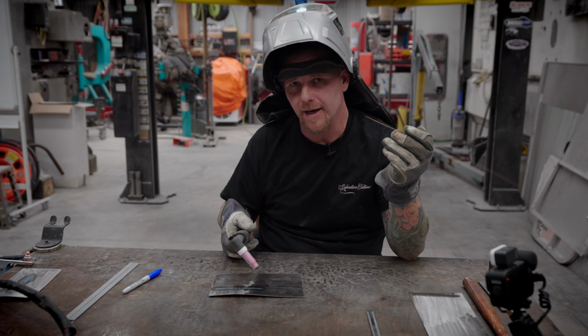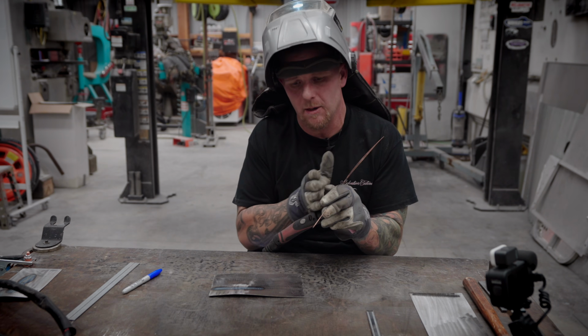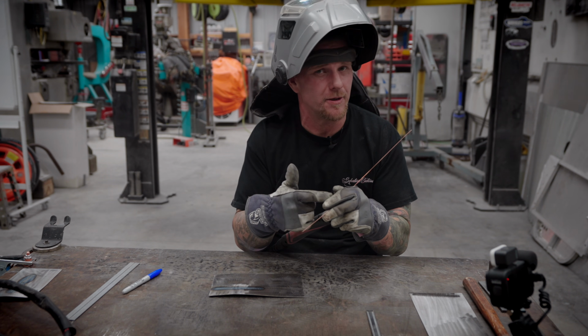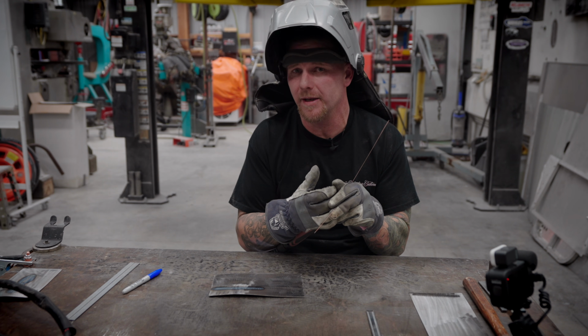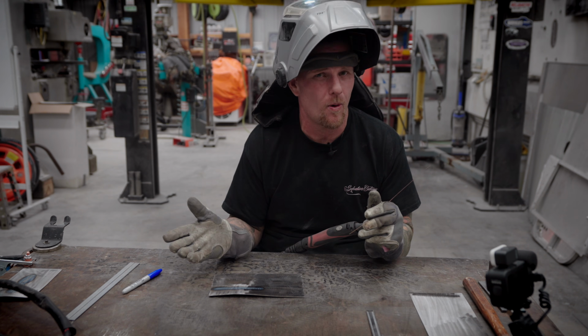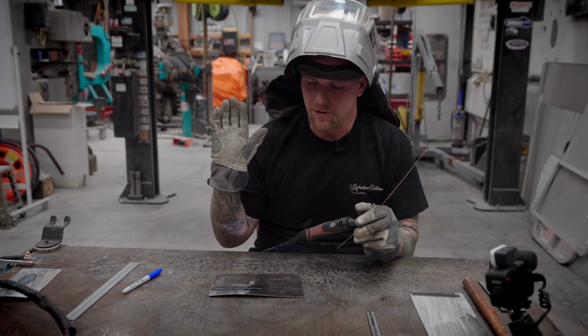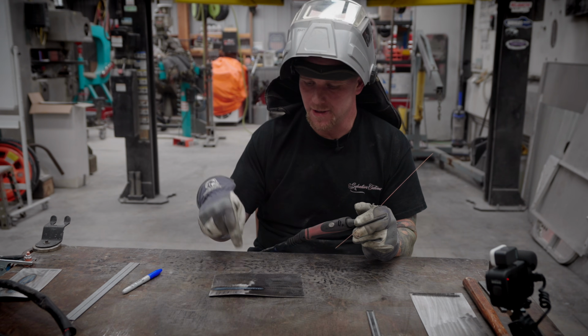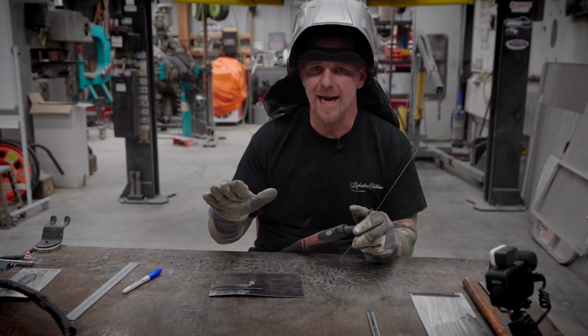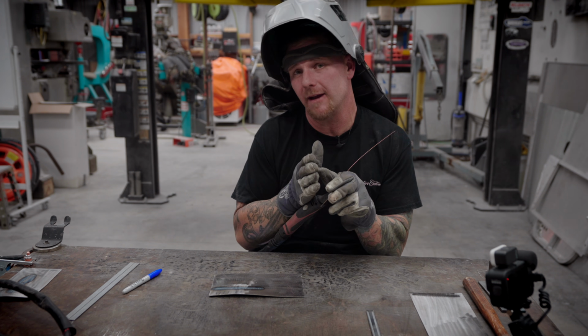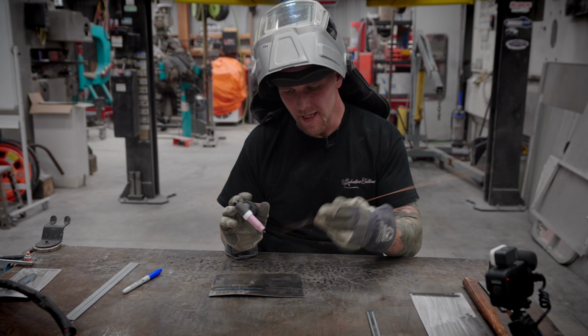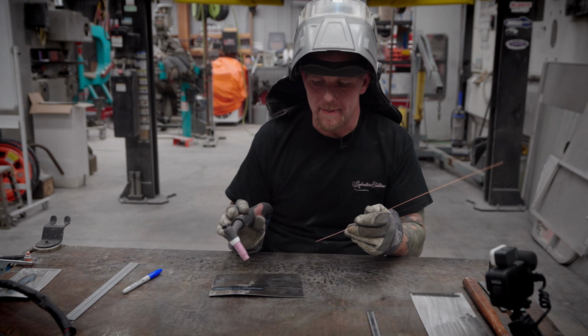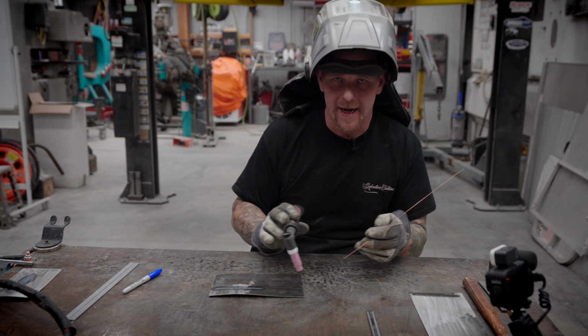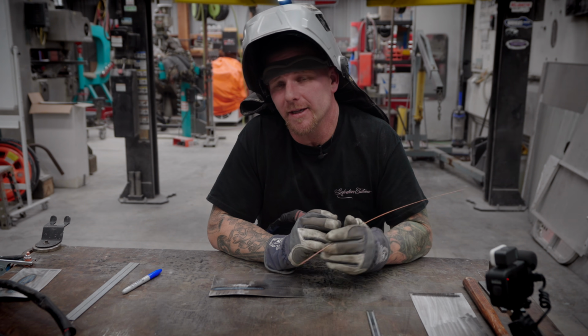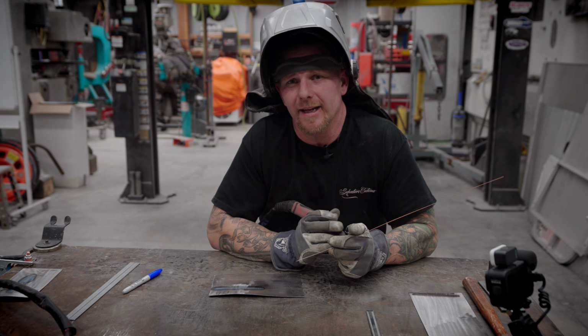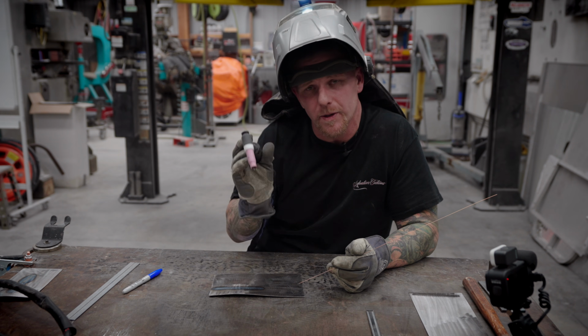If you didn't have filler rod, if you have a gap that is slightly too large, it will want to blow away, opposite of what you would think it would do. It's not always going to pull to the center of the weld. It's going to want to blow away, and then you'll have this massive hole. So what you're doing is you are pedaling down based off of your amperage and thickness. And if you have a gap, you are slightly letting up on the pedal, so that way you can compensate for that burn back on the gap, and then being able to fill that gap. And then when you're back into an area that has a better fitment, you can then carry on. So just remember, the filler rod does not create the weld. It is just filling the puddle that you are already controlling with the torch.